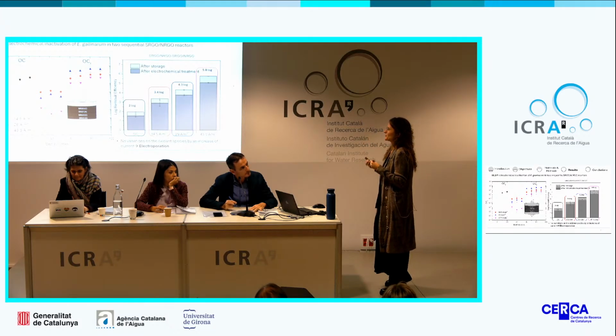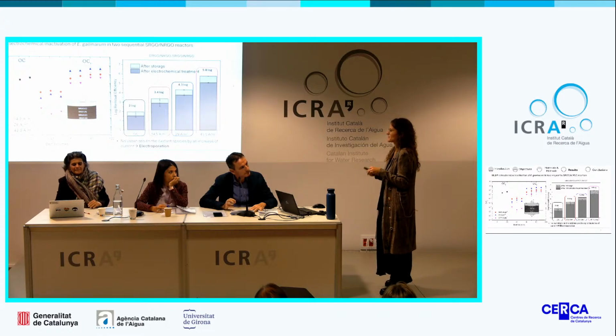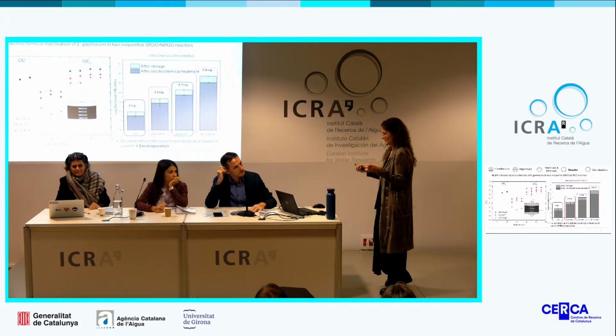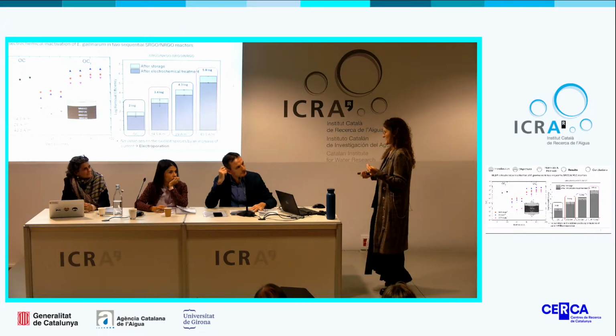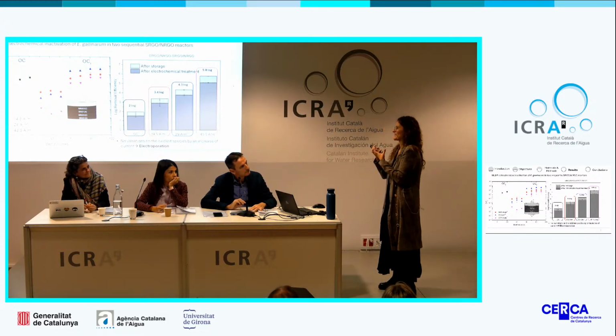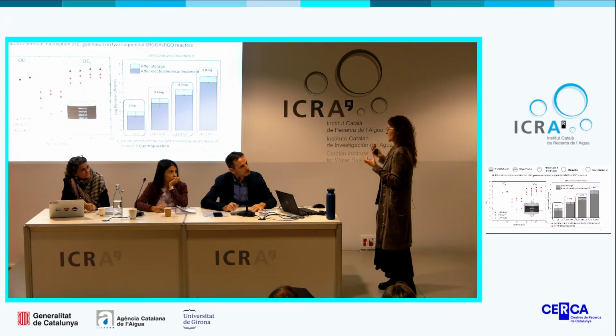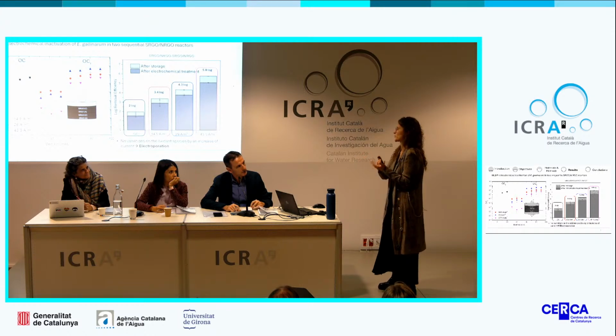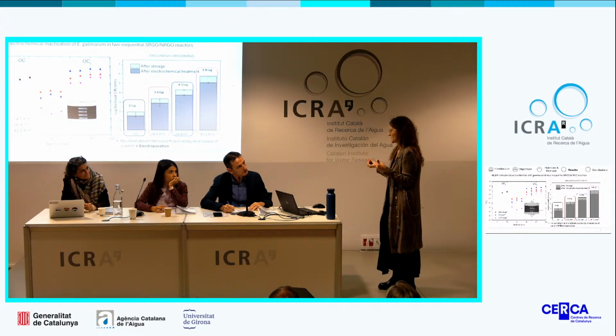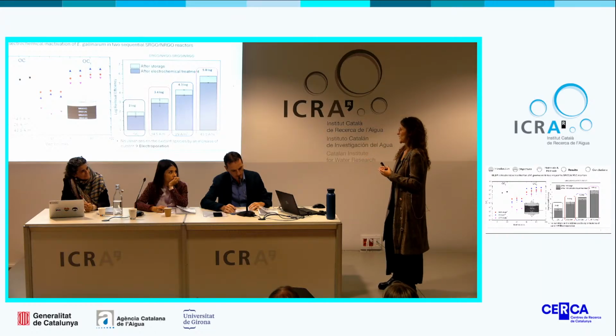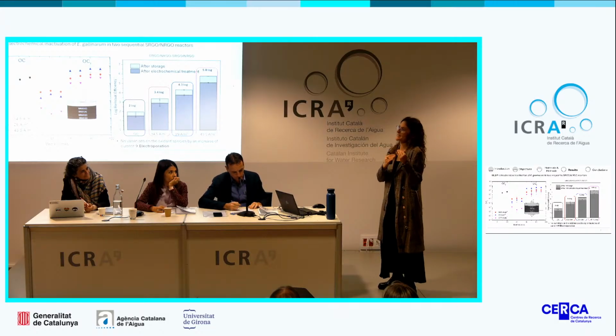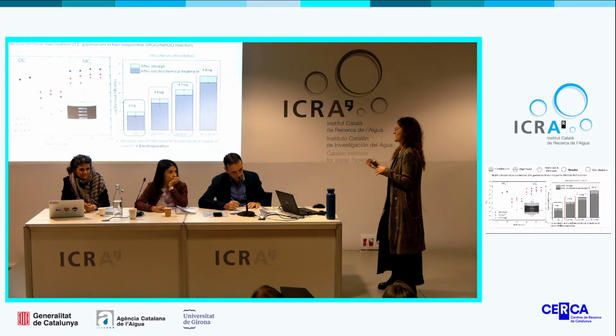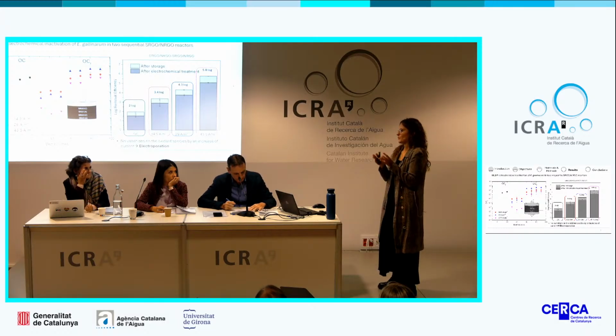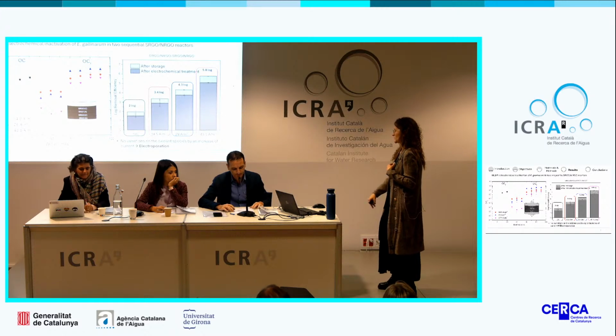Okay. So, we didn't perform a specific experimental study for it. However, we also measured the release of sulfur, in order to see if the coating was stable or not. We also measured sulfates at the highest current application, because in some cases, in the synthesis, we didn't have stable coatings, and we were releasing our coating, and this is something that makes the electrode unstable. However, we didn't perform a specific study in the long term, I will say. Okay, so it's something that must be studied.